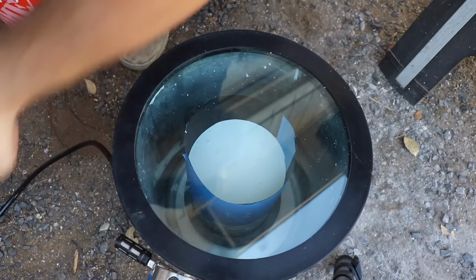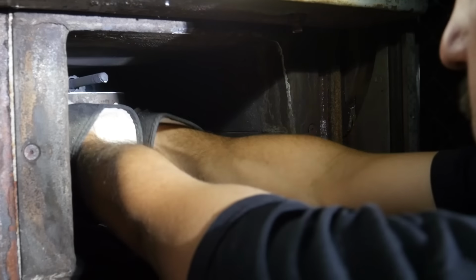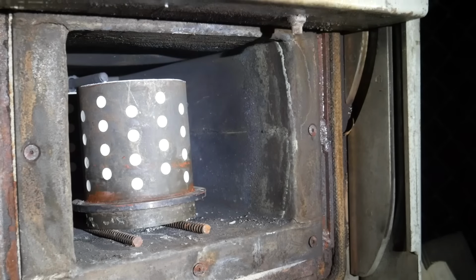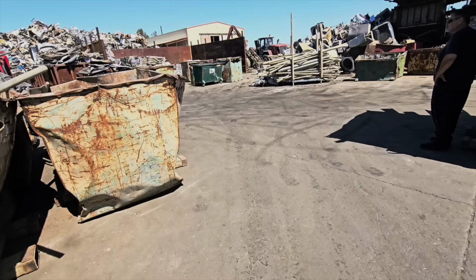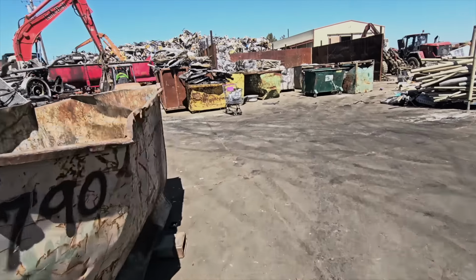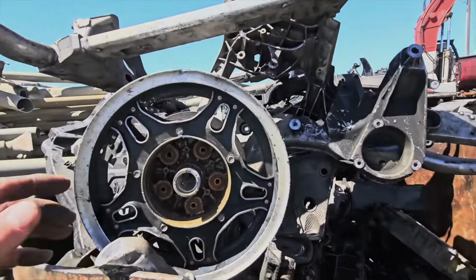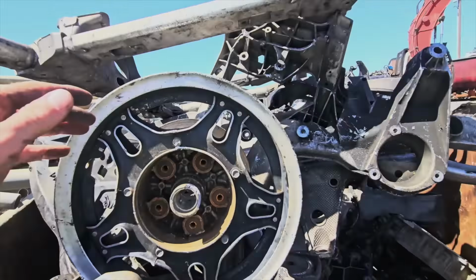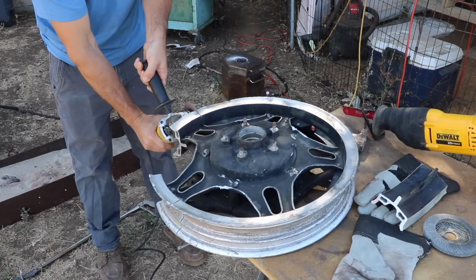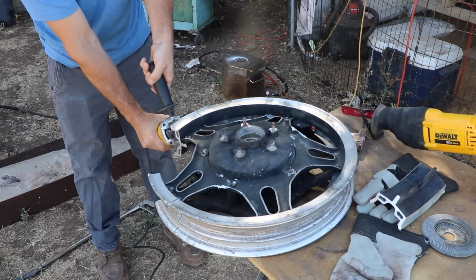The most important factor in this project is going to be creating something that's durable enough to withstand repeated impacts. Because of that, we're going to use A356 aluminum to cast these fairway woods. This alloy is commonly used for car parts, including rims, so Packer went out to the junkyard and grabbed an old tire rim to melt down into our golf clubs. The cool thing about A356 aluminum is that after we cast the clubs, we can do a T6 heat treatment on them, which will significantly increase the strength of the alloy.